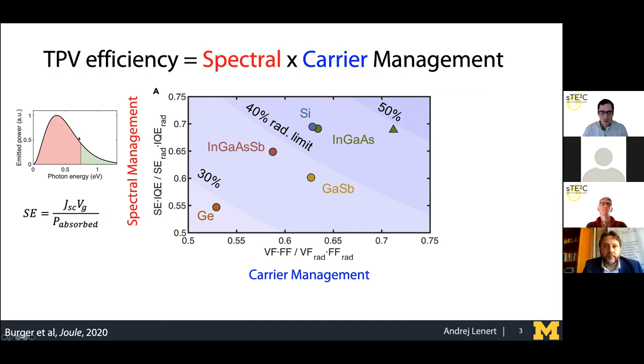So TPV conversion is usually best suited for converting the tail of the black body distribution. So this part shown in green, that's usually where calculations show that the band gap should lie for highest efficiency. And it could be one band gap, it could be two band gaps, but spectral efficiency really captures the photocurrent or the short circuit current that's generated from converting this part of the spectrum times the voltage of the band gap, divided by basically the net radiative exchange between the emitter and the cells.